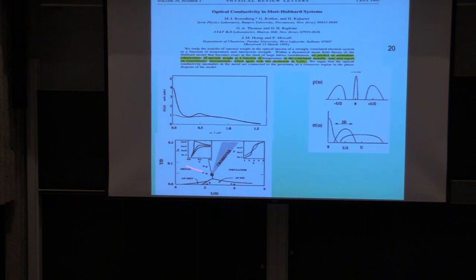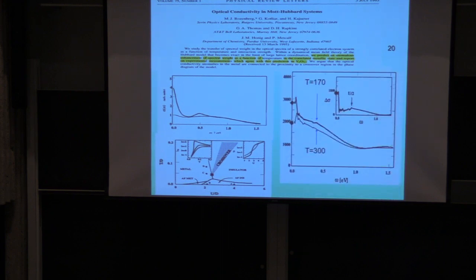if we analyze the phase diagram of vanadium oxide, we can get pretty much a phase diagram like in the experiment. But we also noticed, theoretically, something quite interesting. When we change the temperature by a little bit, the spectral weight gets redistributed over a very, very broad energy scale. This was done with very primitive models very long ago, as soon as dynamical mean field theory was developed. And we predicted, in fact, that we would change the temperature in vanadium oxide by a small amount, by a few hundred degrees, and we would get a redistribution of the whole optical conductivity curve by a large amount. So that was sort of the prediction, and that's how the experiment looked like.